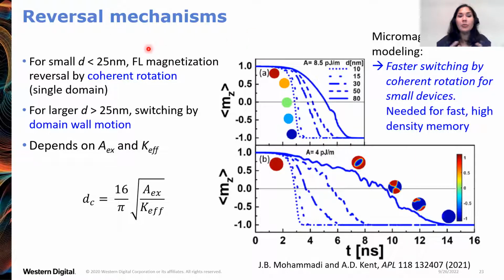So for very small bits, 25 nanometers and smaller, the free layer reversal happens by coherent rotation. It's as if the magnetization of the free layer rotates as a single domain. So this is shown here on the right side. This is a micromagnetic simulation showing these reversal mechanisms. So this is coherent rotation, the red being magnetization pointed up, and then the magnetization rotates as a single domain till it's all pointed down, this blue color.